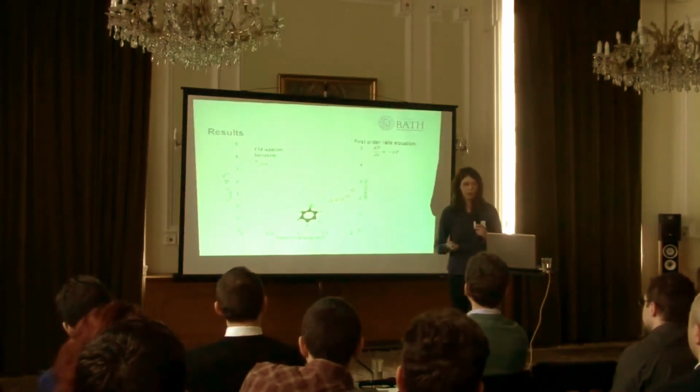So essentially what it's telling us is that it's only the sample that ever does anything, which contradicts everything else that people have known so far. People thought that the electrons go into the molecule, it is excited, it vibrates, and leaves the surface. Instead, the molecule is a complete bystander, and the silicon surface is extremely reactive.